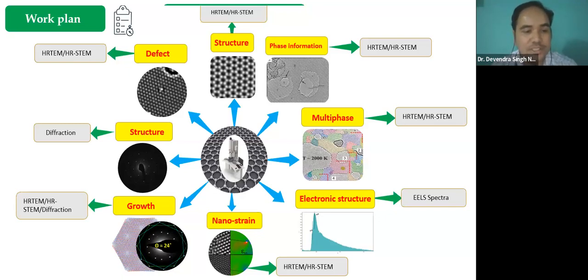If you want to see how the growth is forming, by diffraction based study you can see how the substrate is modifying the growth direction of this material. Microscopy also gives you the answer to how the atomic scale strain is taking place. And of course, there are spectroscopy methods in transmission electron microscopy, which can give you information on how the electronic changes are happening at atomic scale. So this is a one-stop solution to understand all these key challenges. And I just showed from this slide how all these key challenges can be addressed. Next slide.